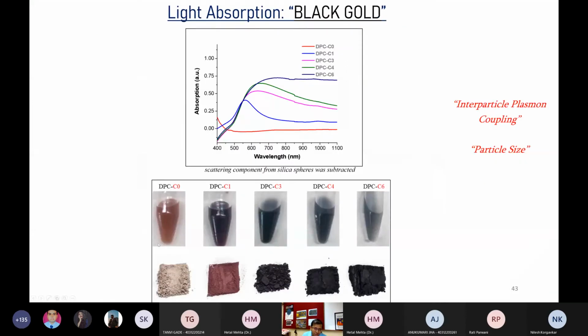Now you see C0 is the gold nanoparticle supported on silica. This is the color. C1, again a gold nanoparticle supported on silica, but the color becomes dark. C3 again darker. C4 is nearly black, and C6 is also black. It's still gold. There is no change in the oxidation state. There is no doping, no functionalization. But color becomes black because now it absorbs nearly all the visible light spectrum of the solar light, and that's why it becomes black. The reason is, as explained, interparticle plasmonic coupling as well as particle distance.